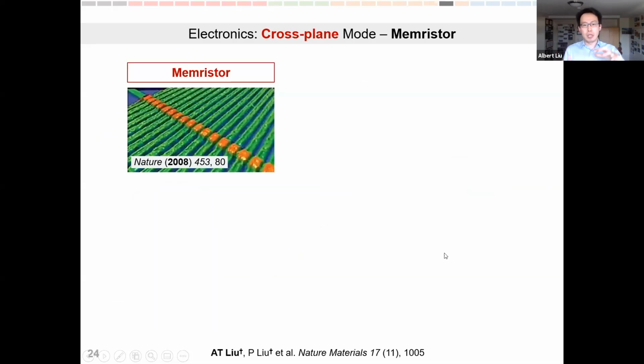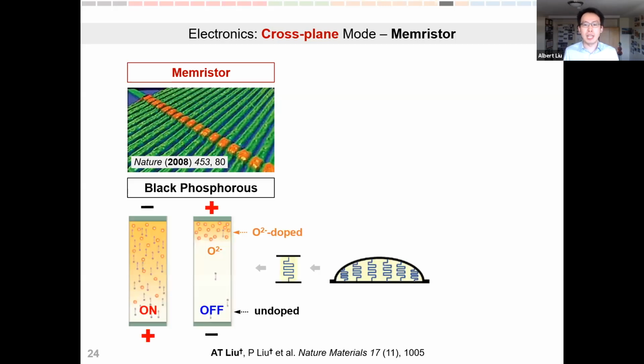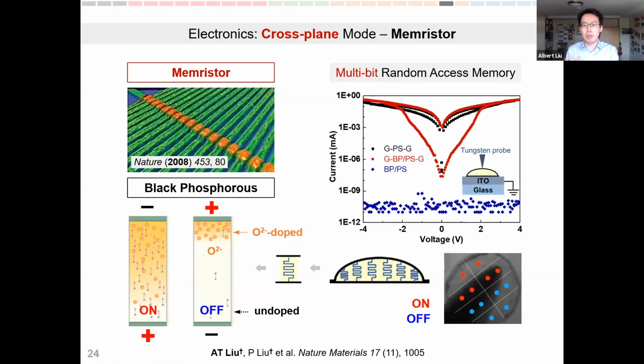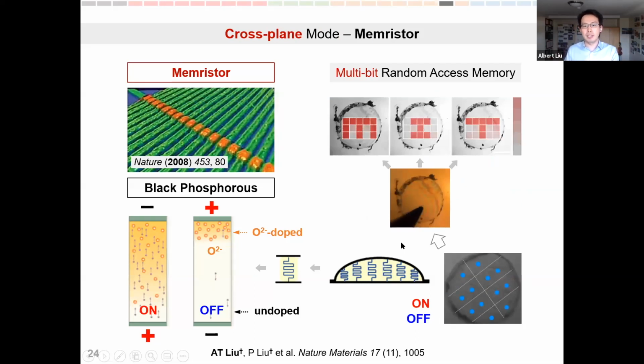In terms of building digital memory into our colloidal particle that is encapsulated by two layers of two-dimensional material, one on top and one on bottom, we leverage the fact that we have a vertical dimension in our electronic circuitry. From top to bottom, we have a two-terminal device. And by printing memory-resistive black phosphorus inside, we can make these vertical memory-resistive pathways that make our particle able to record digital information. So as you can see here from the current-voltage trace, we can write in an electronic memory by turning this vertical conductivity from its off state, or non-conductive state, to on, or conductive state, by driving a positive voltage across, and we can switch it off by driving a negative potential across it. So this then renders our particle into sort of a random access memory device that is also reversible.